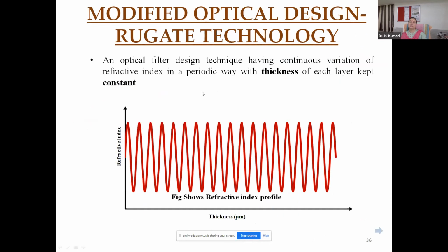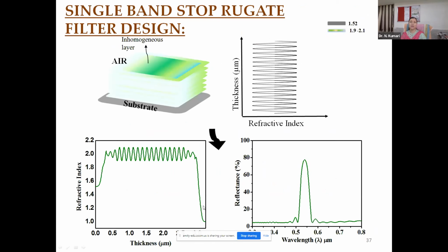And the next one was actually the index modulated design, where the refractive index in conventional layers jumps from one value to the other. Say if we use aluminum oxide and silicon dioxide as a multi-layer structure, we change the refractive index from 1.6 to 1.4 abruptly. That abrupt change in refractive index will result in your side lobes as well as the broadband. So to overcome this kind of problem, we have tried to modulate the refractive index profile in such a way that there is a continuous variation in the refractive index from one layer to the other layer. So using this kind of design, we are able to achieve high reflectance inside the band, and low side lobes as well as low reflectance outside.